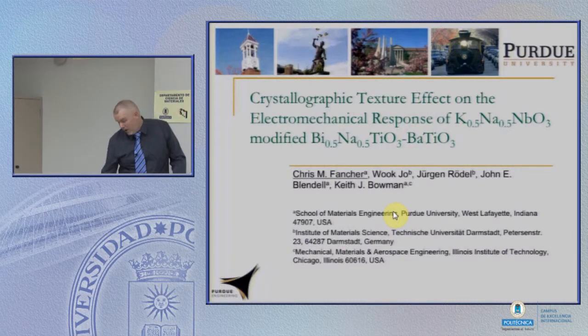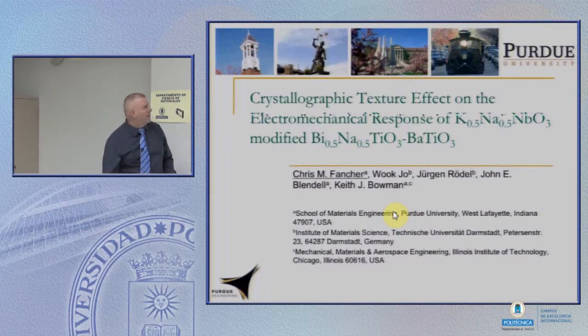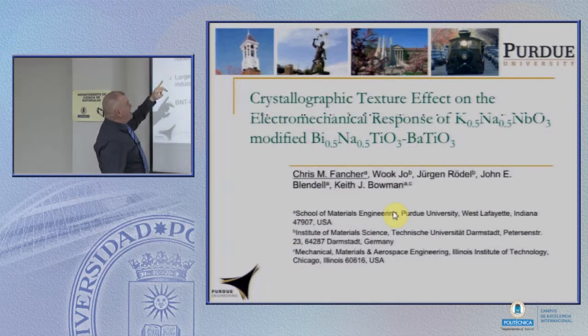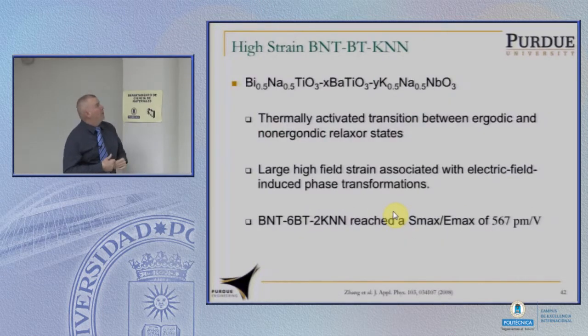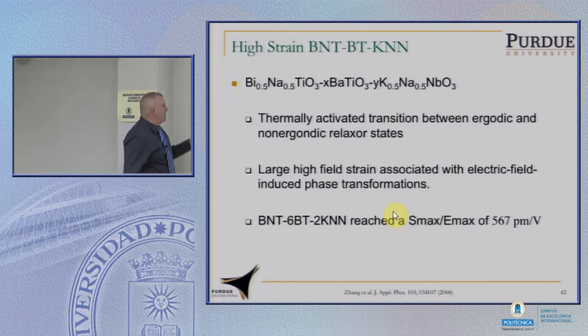But that's where we are with a lot of these materials, is it makes a difference to have these compositions. So BNT, BT, KNN is a material that has been shown to have a very high strain, so-called giant strain behavior by the Darmstadt group. It has a transition that's temperature dependent between a couple different states, which we won't have to describe, but more what we call relaxor behavior, a little bit different behavior than what I've described for the BZT-BCT.